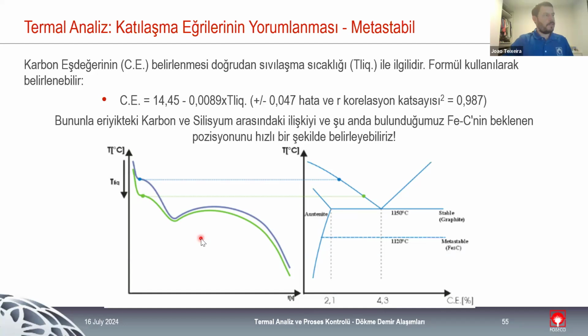And this is just an example for us to understand that different values of carbon indicates different types of curves. We are at the hypoeutectic part, so we are on the left side of the eutectic point, but we have different amounts of carbon, and by having different amounts of carbon, we have different values for the liquidus temperature. So in the case of the blue point, we have a lower amount of carbon, so the solidification is happening really early on. So we are going to have some problems later on because we don't have enough carbon at later stages. So when we are below the eutectic point, you can have some problems with carbon.